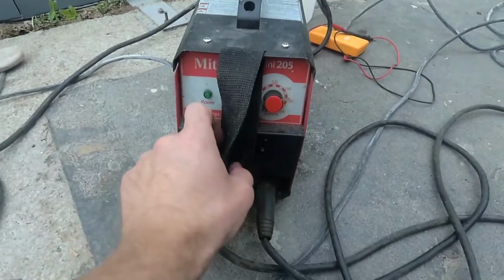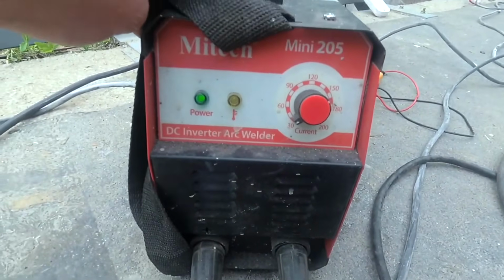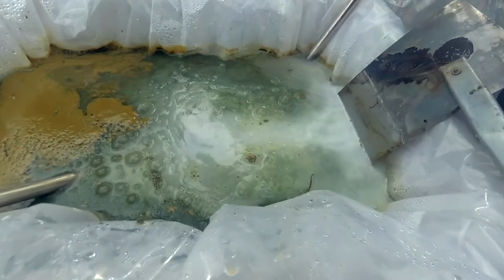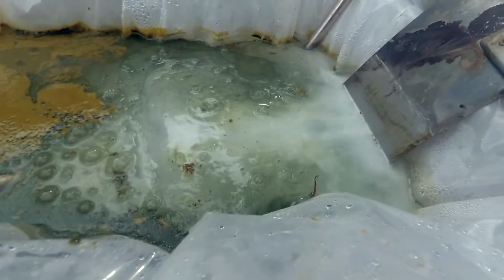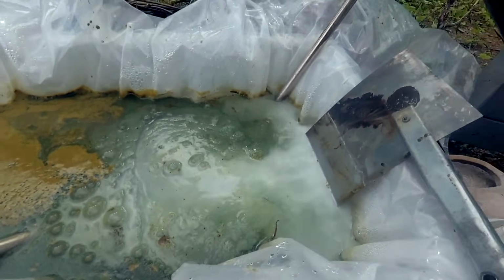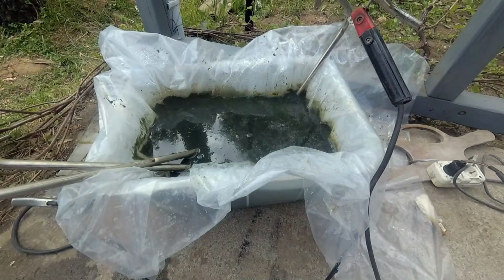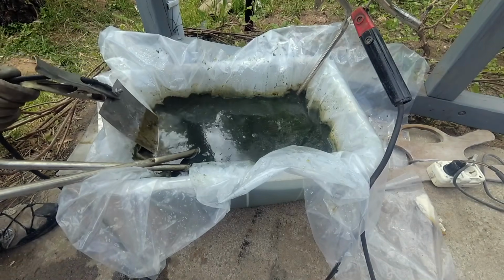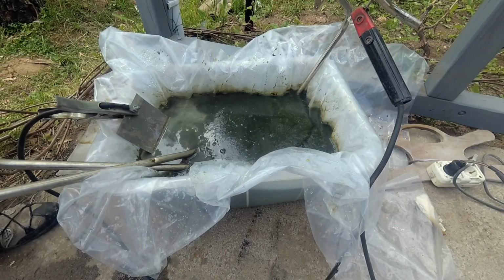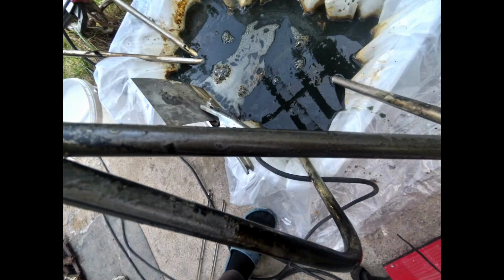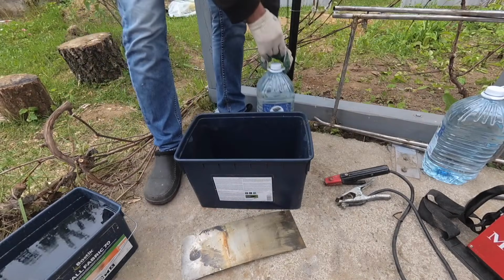I set the welder's amperage to the lowest setting, 30A. The water was already bubbling quite noticeably. After about 10 minutes, the water had turned blackish green. I took the part out. The chrome was starting to come off, but the metal was still showing signs of damage. And it hadn't come off completely, only about 70%. I was afraid to soak it again for any longer, lest the metal dissolve.